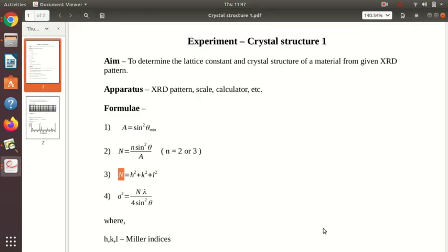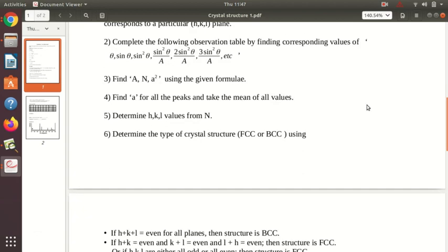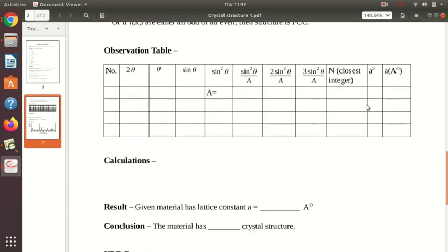So if you get a 7 anywhere in this column, you can just skip this column, whether it is 7 or 15. Usually we don't go for higher values because we get at most 4 or 5 peaks, so we will not use many more values. But if there is a 7 anywhere in this table, you should simply ignore that column.